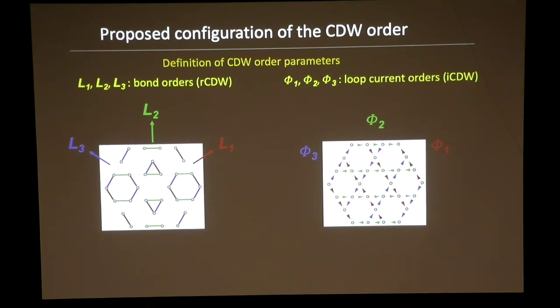The fact that the charge density wave responds to magnetic fields, and the fact that we can show it's real, it's not an artifact, we can do it over and over again, it's also associated with a lattice distortion, tells you that the charge density wave breaks time reversal symmetry. That means that in the absence of spin, some kind of loop current order must exist in the sample.